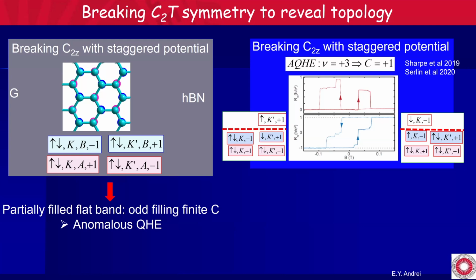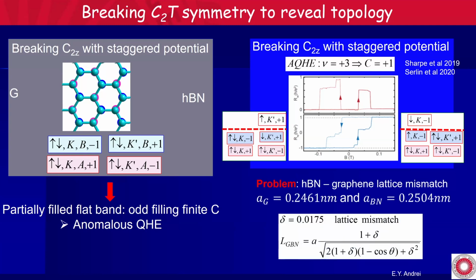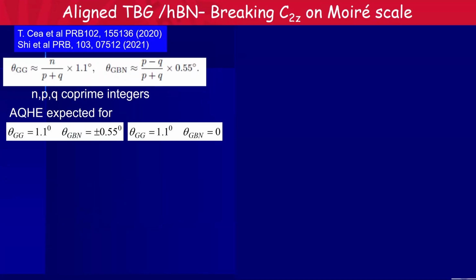Because in fact, contrary to what I drew here, graphene and boron nitride are not identical. They have slightly mismatched lattice constant. And because of that, it's very, very difficult to really break the inversion symmetry. So they have a small lattice mismatch, about a couple of % here. And therefore, as Allan showed and others, the twist angle between the bilayer graphene, theta GG, and the twist angle between the bottom layer graphene and boron nitride, the only way you can align them is if you have these 3 co-prime integers multiplied by 1.1 degree in one case and 0.55 in the other case. And then if you do have that very precise alignment, sure enough, you're going to be able to break the inversion symmetry.